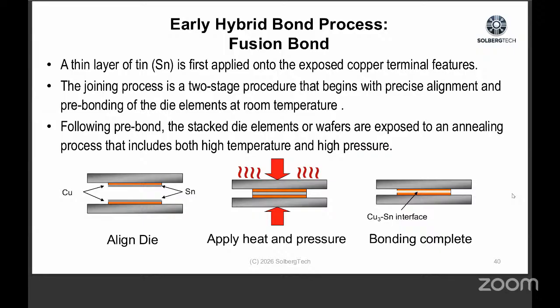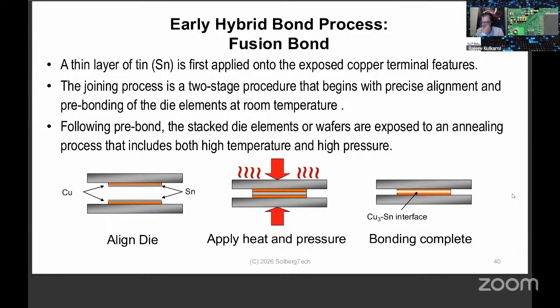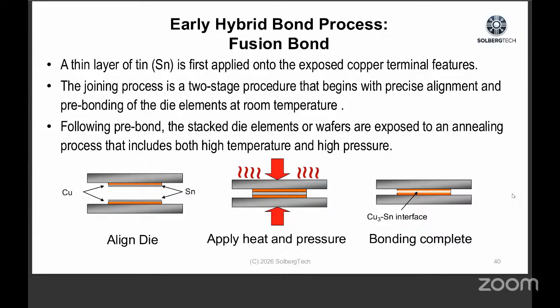So the first attempt at this is what they call fusion bond. This is where the copper terminals on the die and on the substrate or interposer have a thin layer of tin plated onto the surface, and after cleaning, they bring them together. It's a two-stage procedure that begins with precise alignment and pre-bonding at room temperature. That's followed by stacking the elements on wafers and exposing them to an annealing process. It's a high temperature process, and what happens is the materials fuse together, and the tin actually becomes intermetallic with the copper. So you can't see a joint there, but there is no solder, there's no flux. It's strictly a metal joining process. Next slide.